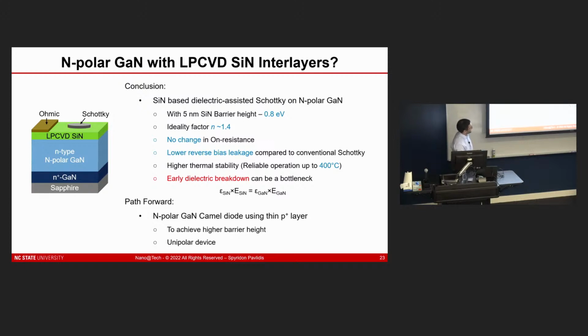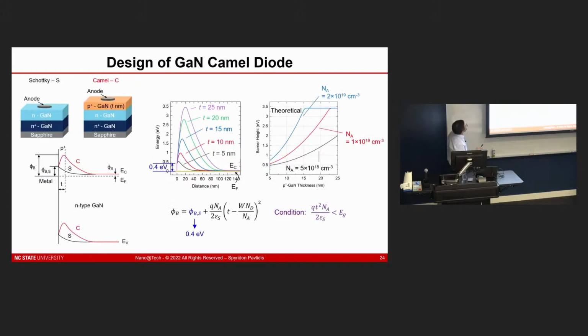So the idea here is to use what's known as a camel diode, and that's what I'll talk about here. So this is, again, your conventional Schottky contact or Schottky diode. And the camel diode is sort of a hybrid or in-between state almost of a Schottky and PN diode. Effectively what you're doing is you're introducing a highly doped P-GaN layer beneath your N layer and your Schottky contact. But you control the thickness of that so that you are able to introduce this hump in the conduction band and therefore a larger barrier compared to your conventional or reference Schottky diode, but you don't go all the way to the point of turning this into a PN diode. So this becomes a depleted layer effectively.